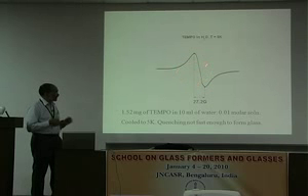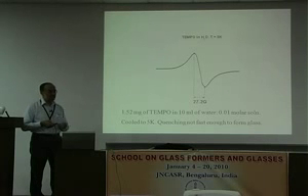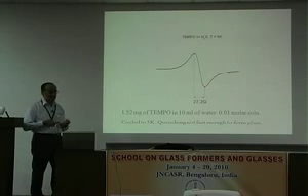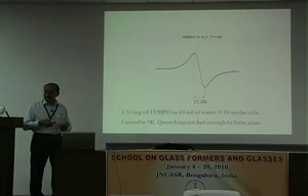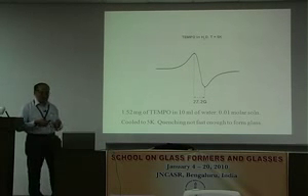Without going into the details of the basics of occurrence of the signal, let me say that any crystal does not want to have any impurity in its lattice, so it throws it out. So, when the TEMPO is thrown out, you get an aggregated ESR signal like this, which is an indication of the occurrence of the water crystal. So, if you see this shape, that means that you have crystalline water.